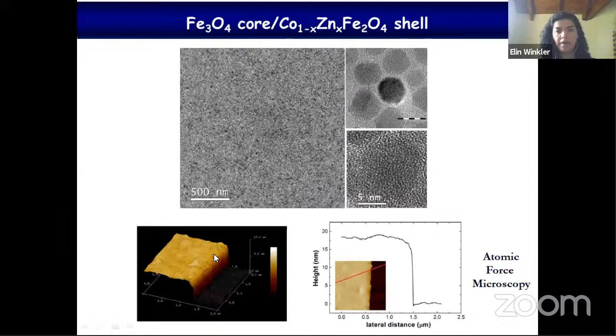And this, for example, is an atomic force microscopy image, where we measure a profile, and you can see that the width of the self-assembly is approximately 20 nanometers. And remember that the size of the nanoparticles is 10 nanometers. So this means that the self-assembly is formed by 2 layers of nanoparticles. And you can observe that here we have more than 1 micron, so there are many nanoparticles. The area is very, very large.